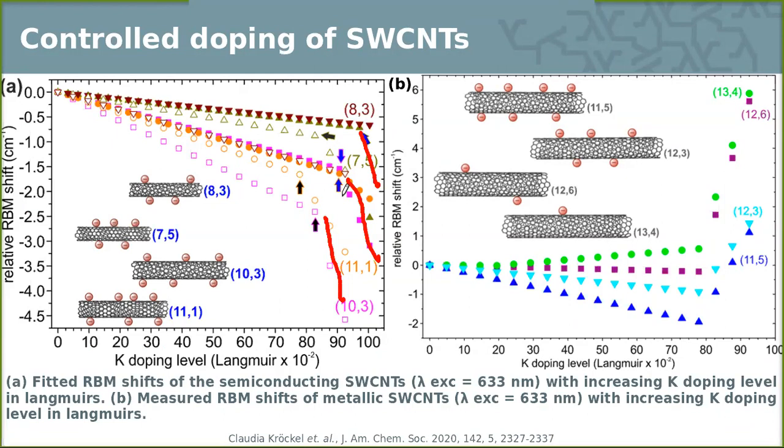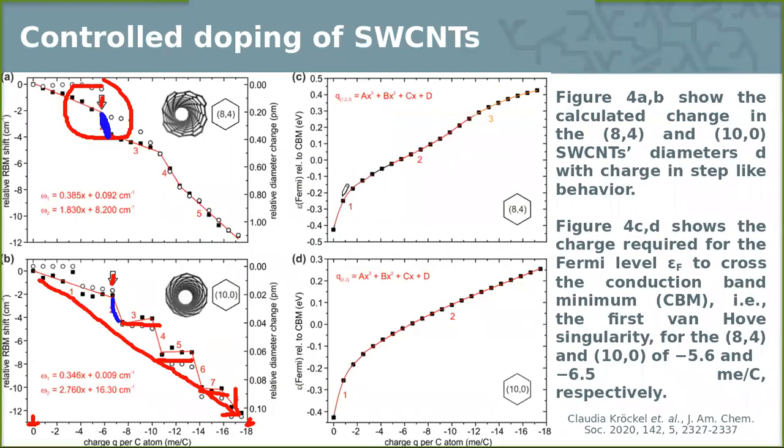But then what's the meaning of that? Why do we have this kind of situation? The reason is because according to this graph that we observe here, as we increase the amount of electrons, we also displace or shift the Fermi energy level with respect to the conduction band minimum. That means that we are crossing the Fermi energy level.